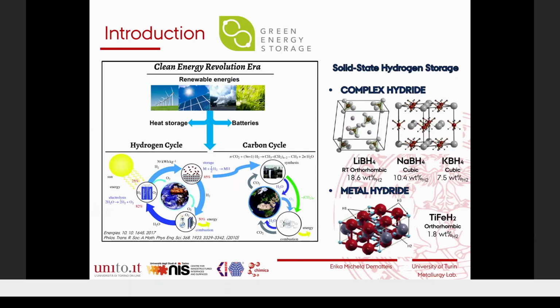In our research group, we are focusing on the solid state of hydrogen storage. That's because in the solid state, hydrogen can be stored in a really safe and compact way. So with low weight and small volume, we can store a great amount of hydrogen. And this can be done with complex hydrides, which are inorganic materials that can go up to 18% by weight of hydrogen stored in the case of borohydride. As shown in the figure, lithium borohydride can reach this high gravimetric capacity.